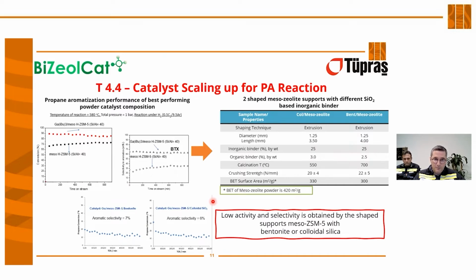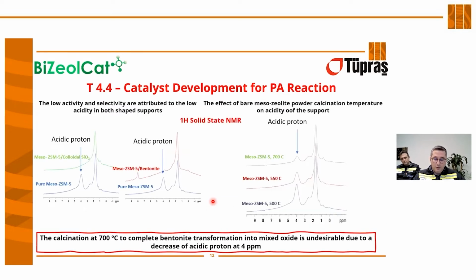So we had to improve this performance by reducing the inorganic binder and also reducing the calcination temperature after shaping. This can be explained by the reduction of acidic proton seen at 4 ppm in the solid state NMR results. When we add inorganic binders, this peak disappeared. When we increase the calcination temperature up to 700 centigrade degrees, we also see an acidic proton peak in the spectroscopy, but the intensity of the peak is lower.